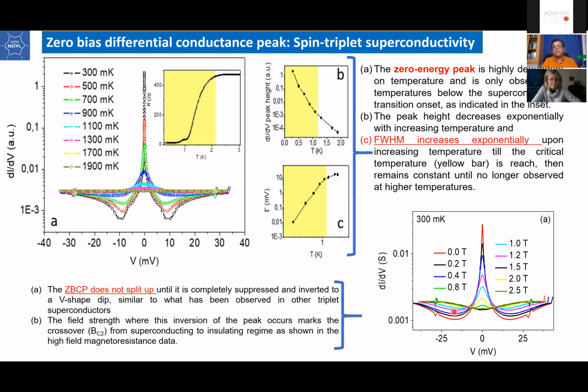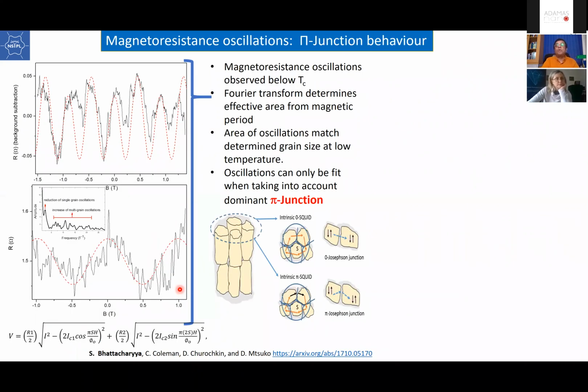So if you perform this experiment as a function of magnetic field, you can also record these things. It's sensitive to magnetic field. Although we published the paper, there are many, many things to be understood in the material. To be frank with you, we are doing more calculation and simulation of the data. Anyway, there's one more interesting thing which is not observed in BCS type superconductors, because you have the junction, grain boundaries. Remember that I said the junctions or boundaries are very, very important in the superconductor. So you can create a junction which is called a pi junction. So you can have a pi phase change of this superconducting phase. And you can see this periodic oscillation at different temperatures. We have many more data, but I'm just showing you some of them.